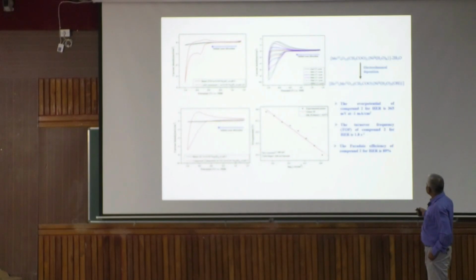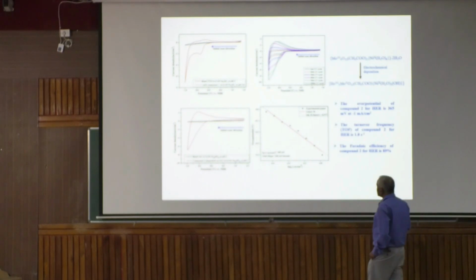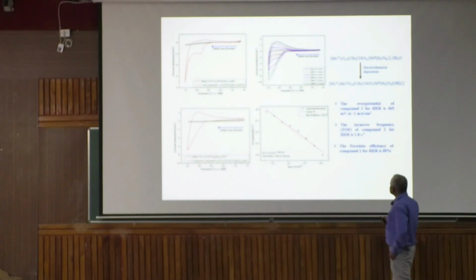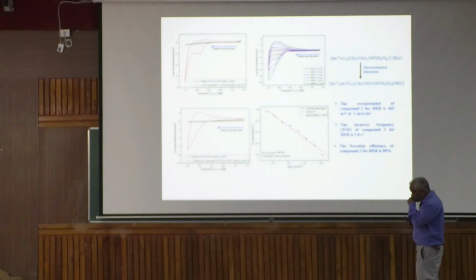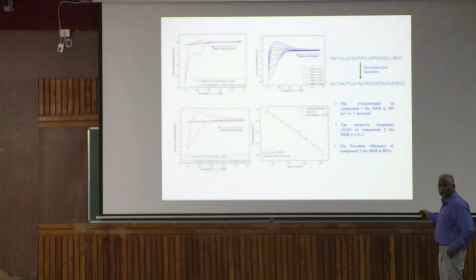So what we believe is that molybdenum is 5+, and that remains the same even after you do the XPS. But nickel 2 goes to nickel 1 and nickel 1 reduces water. I come back to nickel 2 and make the cycle. So I'd like to draw your attention that this compound, the material that is deposited, is also not anymore MoO3, it is MoO3 but molybdenum bronze.